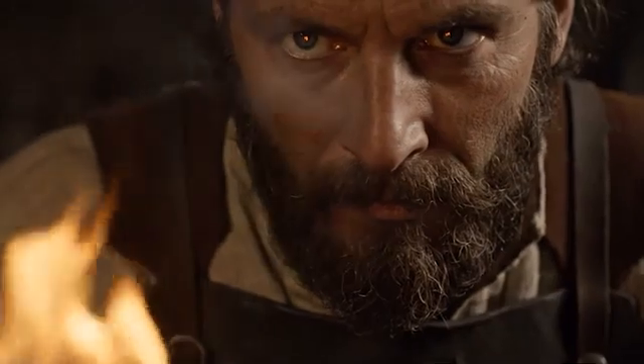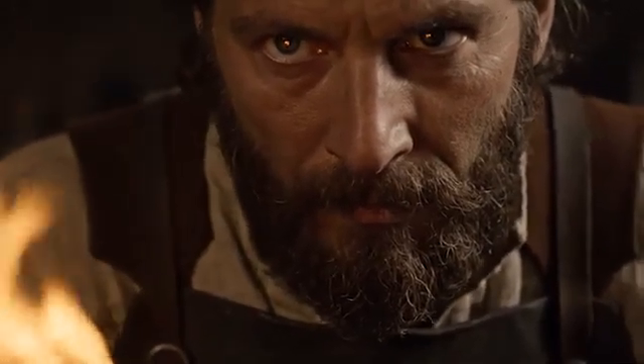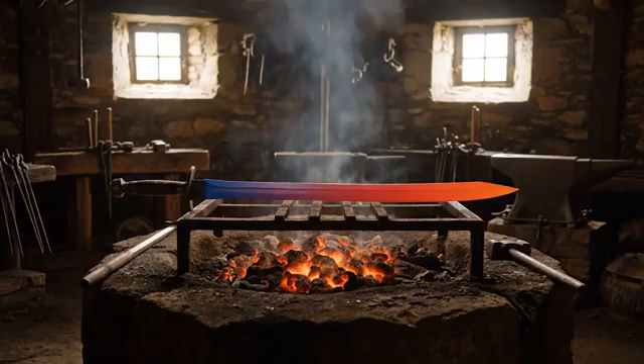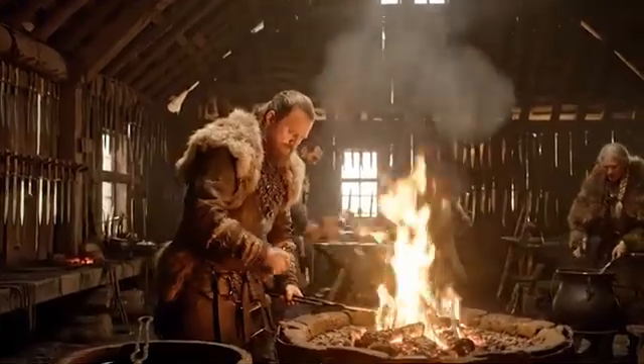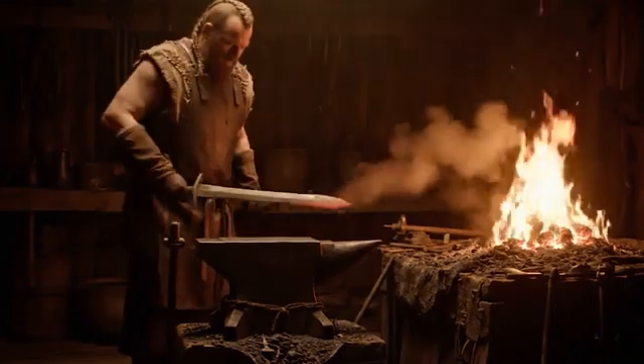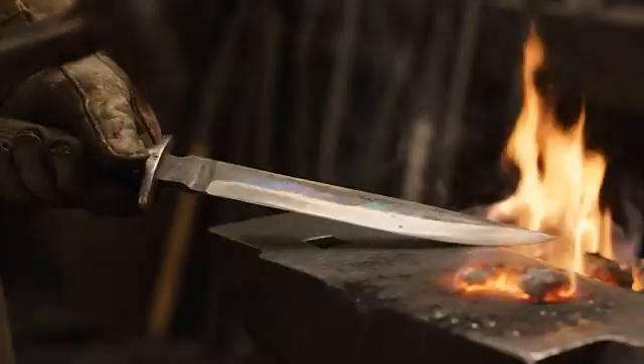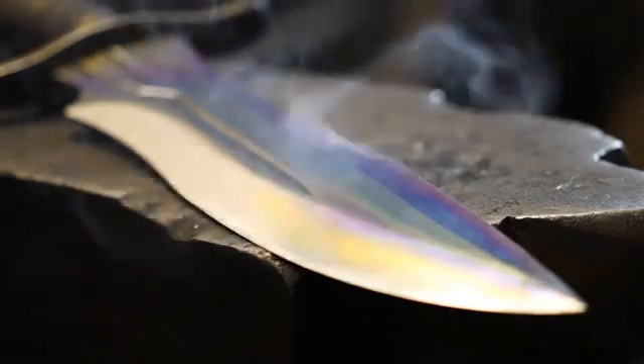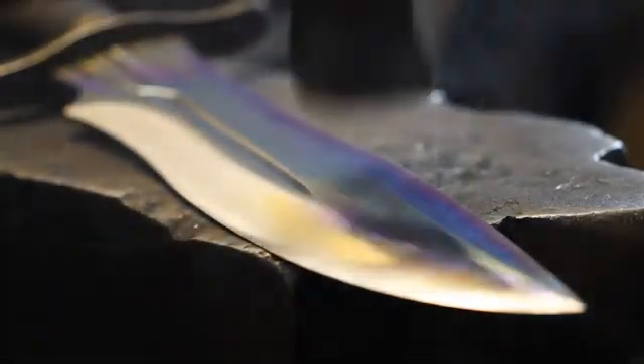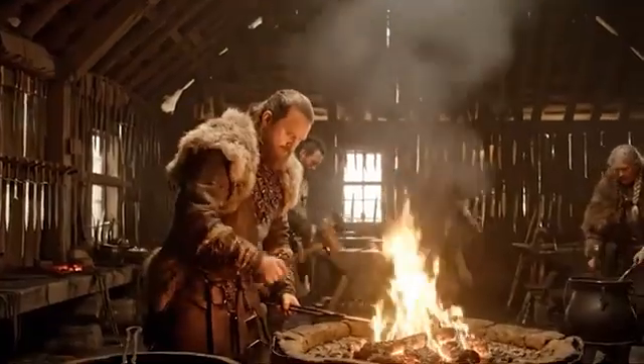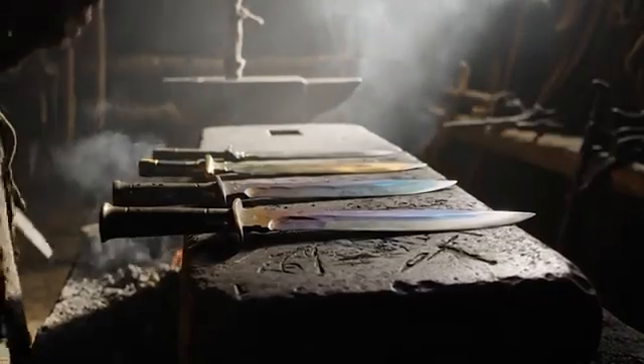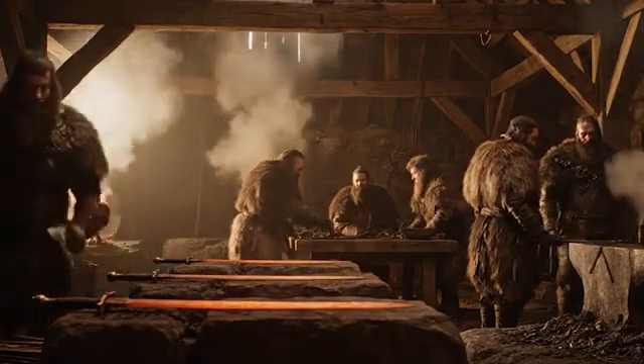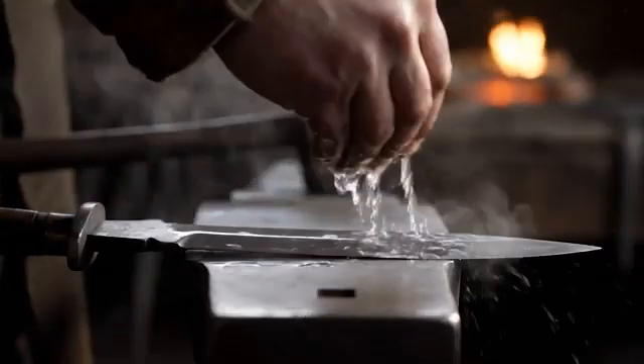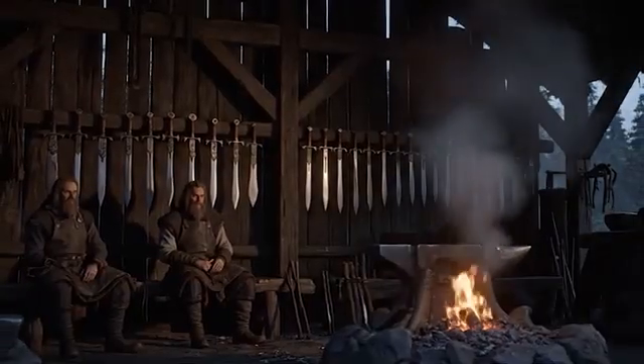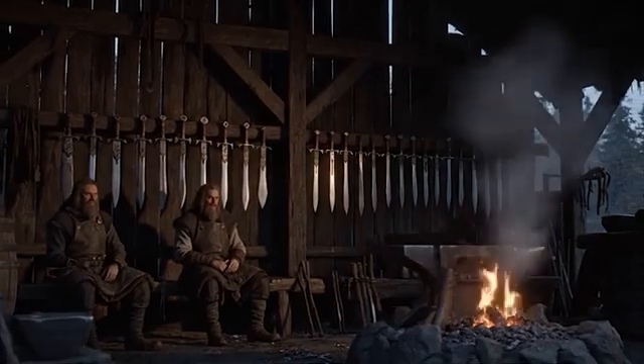To relieve internal stresses and give the metal the necessary toughness and elasticity, a second stage was required: tempering. For tempering, the hardened blade was heated again, but to a much lower temperature, around 200 to 300 degrees. At this temperature, so-called temper colors appeared on the polished surface of the steel, ranging from light straw to blue. The craftsmen used these colors to judge the temperature and degree of tempering. Once the desired color was achieved, the blade was cooled again. Tempering made the steel slightly less hard, but significantly more durable and elastic. It is this balance of hardness and toughness that is the main characteristic of a high-quality blade.